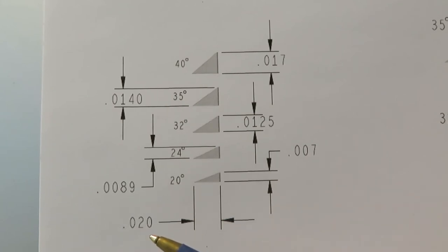So if I look at a twenty degree angle, which is this one right here, and I come back at twenty thousandths, my blade thickness where it's susceptible to curl is point zero zero seven, or .007. There is not much material here to work with. Jumping up to twenty-four or twenty-five degrees like the cutthroats, we go from .007. It's only been four degrees over that twenty thousandths, but we've jumped a lot in material.